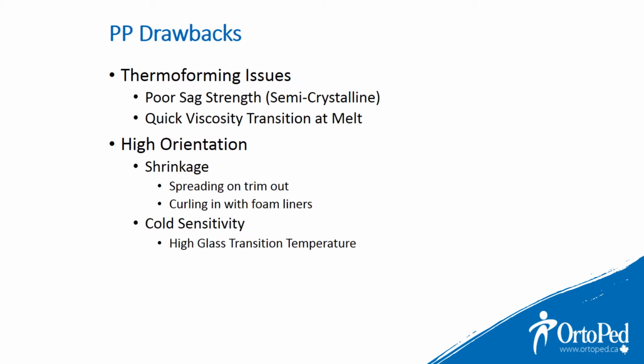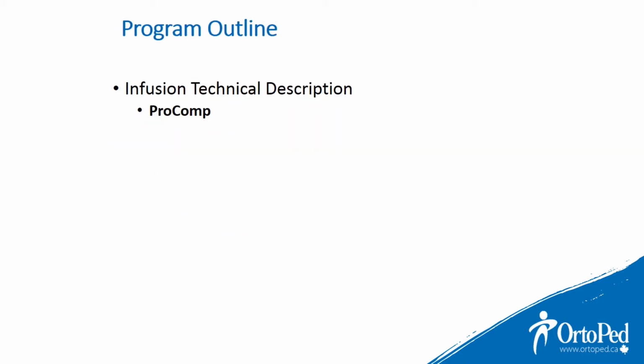Some of the drawbacks with polypropylene: thermoforming issues, poor sag strength at a semi-crystalline state, quick viscosity transition at melt state, shrinkage, which is always a big concern, spreading on trim cutout, curling with foam liners, cold sensitivity, high glass transition temperature. Let's look at ProComp in more detail.